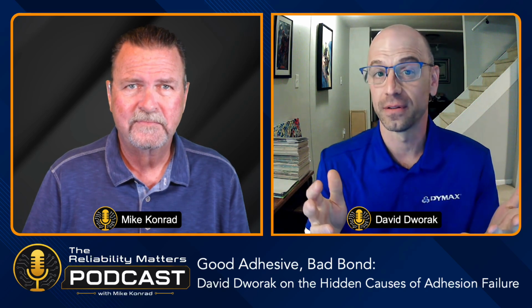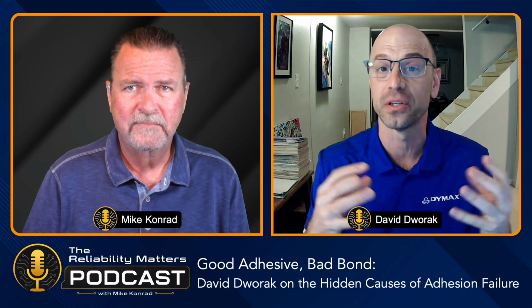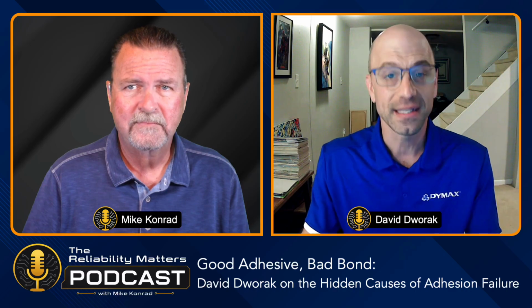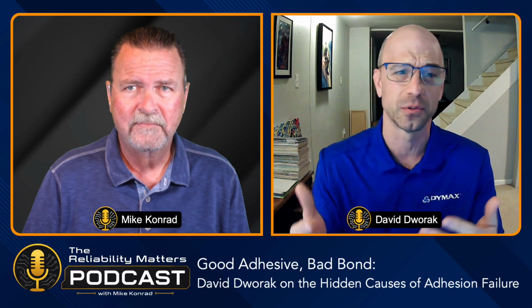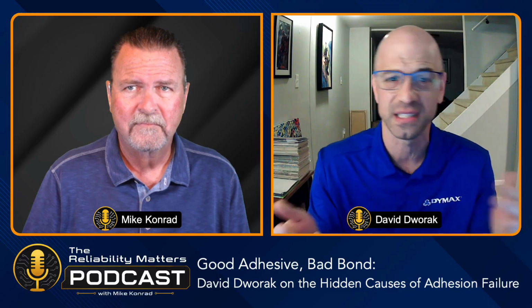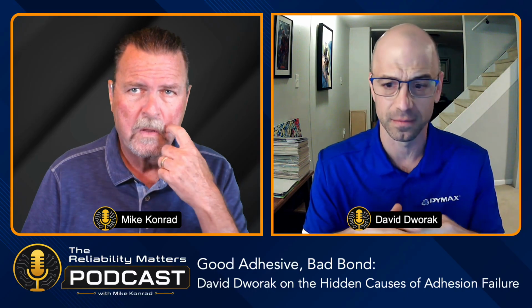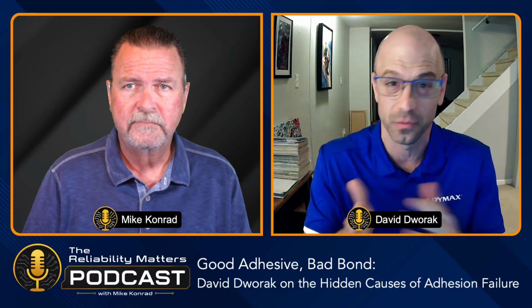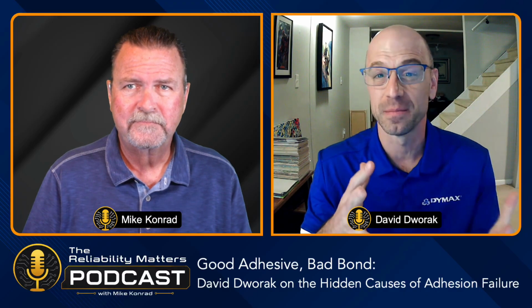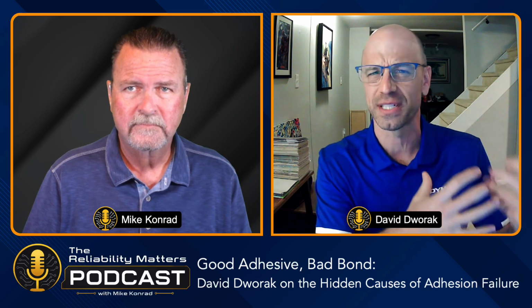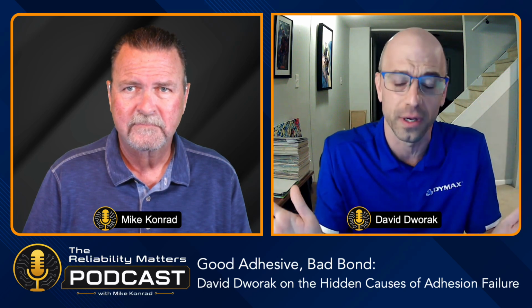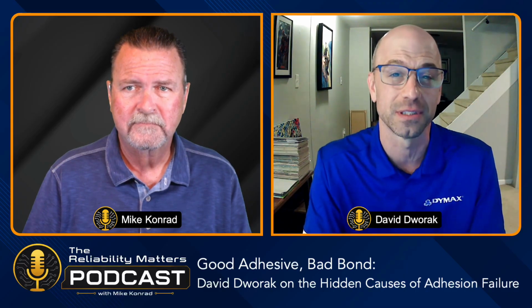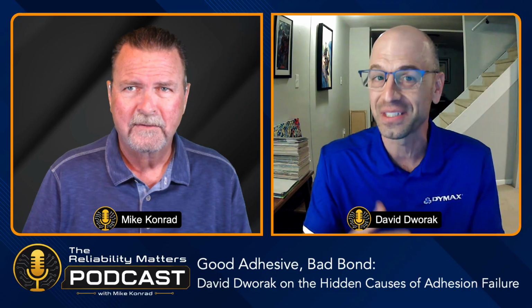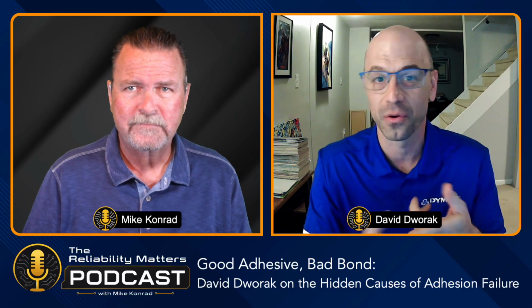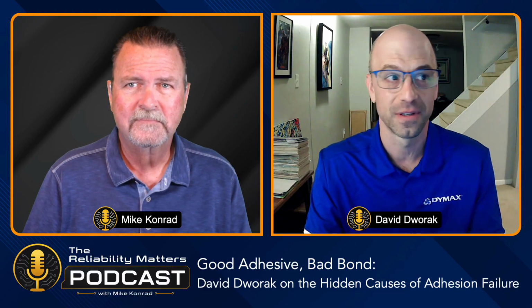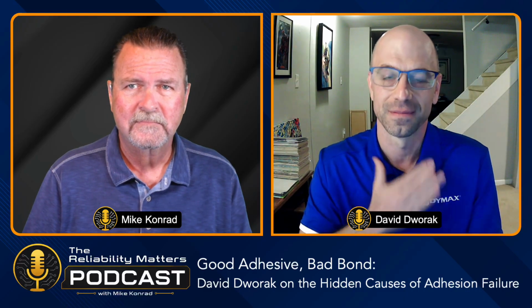Right. And then there's substrate failure, and that's where the adhesive was totally intact, but your substrate itself failed. And if that's the case, now you look into your substrate for possible sources of weak areas: micro cracks, voids, over treatment. That's where you want to start focusing on your substrate. And there might be some design issues too, where that area is stressed more because of the design of the component. There's a lot of areas that you can look into when it comes to substrate failure. So yeah, a lot of things to check out when a bond fails. Again, how it failed, contamination, the adhesive itself, a lot to focus on instead of just the adhesive.